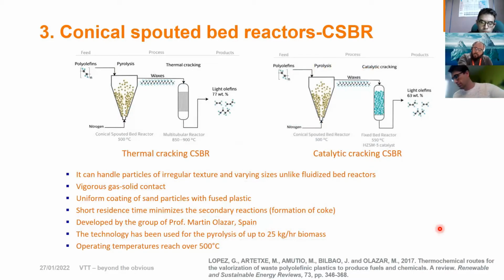Conical spouted bed reactors are, again, fluidized bed reactors, but with a different geometry. The reactor is basically a cone-shaped reactor, and this is done to maximize the solid mixing regimes. So the mixing in the fluidizing medium is quite good. It can handle particles of irregular texture and varying sizes. The proprietors of this technique claim that you can have different sizes of material going into the reactor and it will not be a problem. It gives very vigorous gas solid contact. So when fluidization is happening, the gas solid contact is quite good. There's a uniform coating of sand particles with fused plastics, so the mixing of the plastics that go inside is quite good.